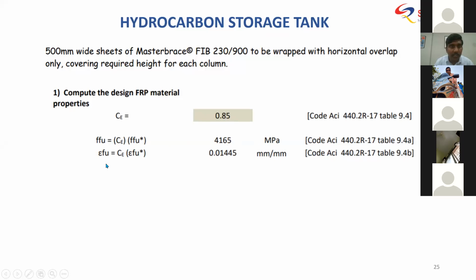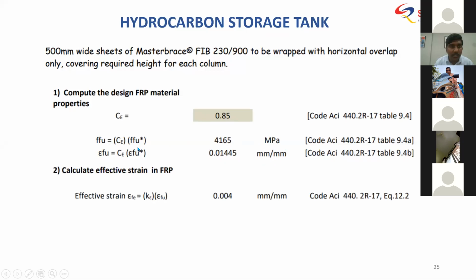And epsilon FU is the ultimate fiber strain of the FRP, which is again reduced to 0.01445 millimeters per millimeter. So the stress and strain capacities are reduced by this environmental factor. Then your effective strain is again reduced by kappa epsilon, another factor. This restriction is there: it can go up to a maximum of 0.004.